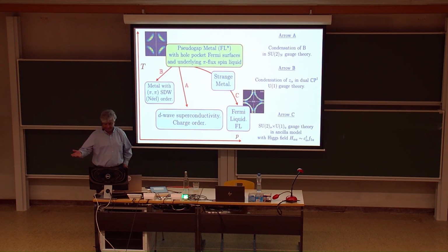So this is the more recent work. You start from this pseudogap metal. When you go across the quantum critical point to the Fermi liquid, you get a strange metal behavior. If you confine it with these Higgs fields, you get D-wave superconductivity and charge order. This all comes out. This is not something that's put in by hand. Or you condense the bosonic spin-ons, you get pi-pi and Néel order. And I'll leave it at that. Thank you very much.